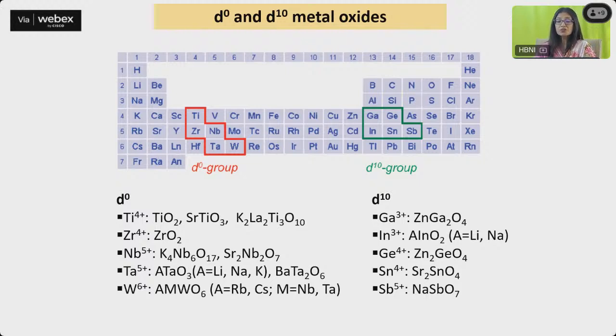Another very important thing to note is that when we are talking about photocatalysis materials, d0 and d10 metal oxides are the most coveted ones. So what are the d0 materials? Like titanium 4+, you have titania, you have strontium titanate, you have K2La2Ti3O10. So these kinds of d0 materials. Then you have zirconium 4+, so zirconia, niobium 5+, tantalum 5+, tungsten 6+. So these metal oxides are going to be good photocatalysts. Then another set is the d10, like gallium 3+, zinc gallate, then indium 3+, then you can have germanium 4+, tin 4+, antimony 5+.